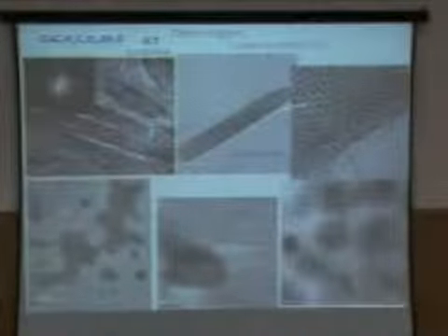So in the high resolution transmission electron microscope, you can see these very ordered structures, and this is called the fast Fourier transform or the electron diffraction. This is in the reciprocal space, this is the real image, and that shows these fine spots, and that is an indication of a very highly crystalline nanorod. Now we can change this highly crystalline rod to an amorphous rod.